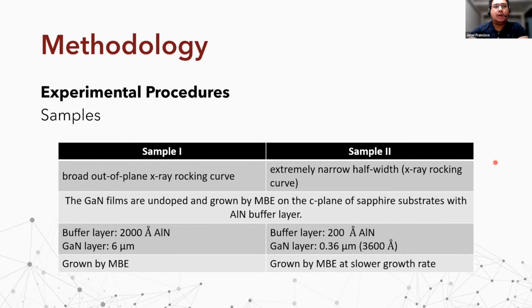The gallium nitride films are undoped and grown by molecular beam epitaxy on the C plane of sapphire substrate with aluminum nitride as the buffer layer. Sample 1 is evidently, as we can see in the values here, thicker than sample 2. The buffer layer for sample 1 is 2000 angstrom with a gallium nitride thin film of 6 microns, while sample 2 has a 200 angstrom buffer layer and a 0.36 micron gallium nitride layer. As I have mentioned, they are both grown by molecular beam epitaxy. However, sample 2 is grown at a slower growth rate relative to sample 1.